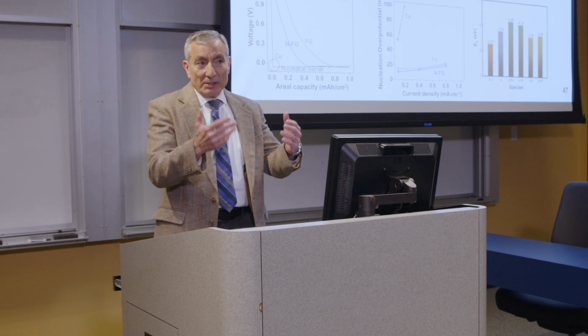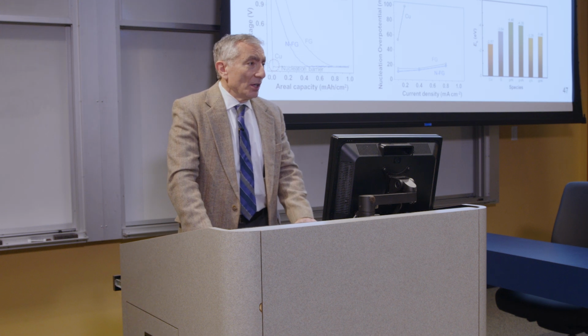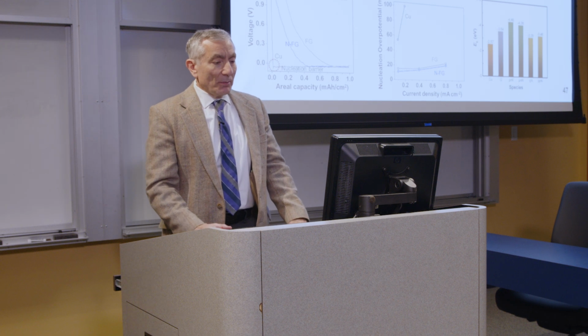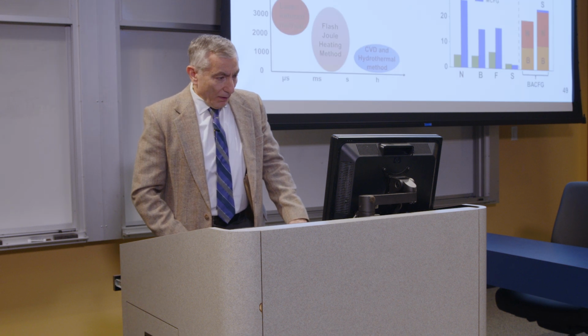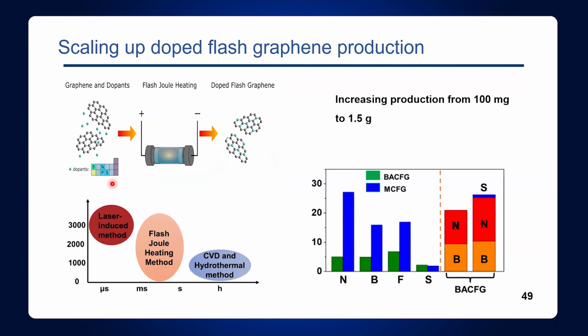But this is something that several of you are going to actually end up doing in your lives, where you're going to have to think about the patent work on this. Okay, so here's where we scaled this up. So we did it on a larger scale. So remember, the laser-induced graphene is in microseconds, just growing on a surface, which we first learned about in CVD method for growing monolayer, takes seconds to hours. This flash joule heating is in milliseconds to a second in this domain. So it's showing you the different domains of time where you're applying this.